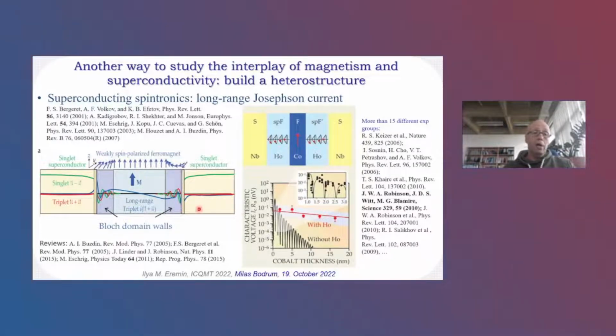So this is, for example, one of the early experiments in this field, where you have two superconductors and a spiral ferromagnet with rotating magnetization, holmium, and a ferromagnet, cobalt, where you can clearly see that without holmium, so without this rotation, without this spin spiral, your Josephson current is strongly suppressed.